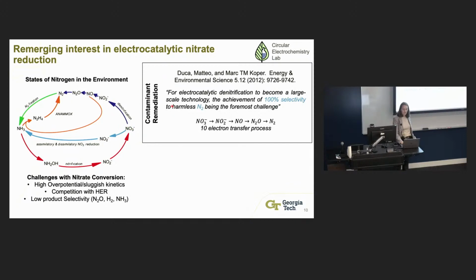And it was interesting in the early 2010s, a group out of Mark Koper's lab basically said, this is a 10 electron transfer process, so that's a lot of electrons that you need to convert nitrate to nitrogen gas, because for the most part, people were looking at this for remediation, as I mentioned, water treatment. And so it was deemed really not going to be possible unless you could get 100% selectivity. What selectivity means is I want to go from nitrate all the way to nitrogen, but I have to go through all of these intermediates, and so they all have to go in a series. Sometimes a reaction can stop at an intermediate, and it may not go all the way to nitrogen. So that would decrease your selectivity.